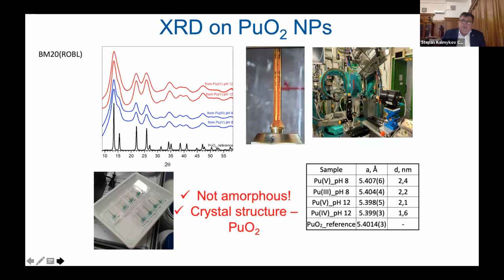So we start with X-ray diffraction, and we can see that there's no amorphous contribution, that there's a broadening of lines, and the broadening is certainly because of the nano size of the particles, and the size was determined. The size is quite close to what we have from the TEM measurements, so this is a good thing.